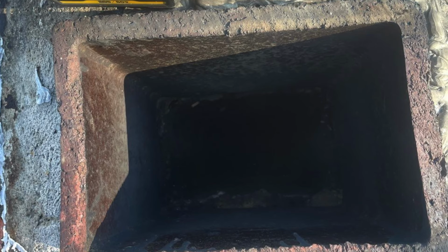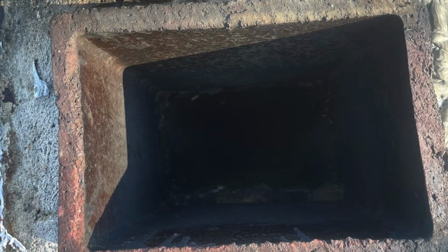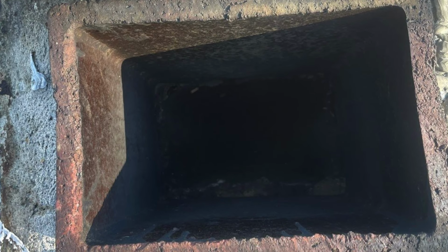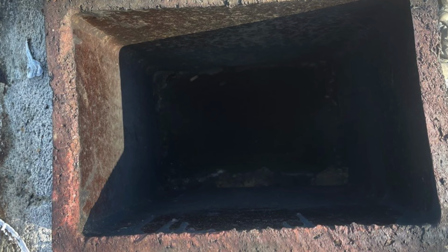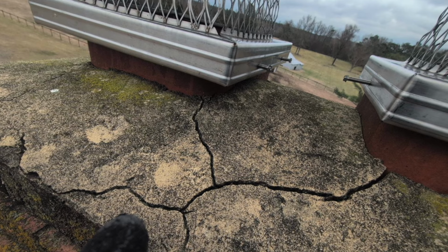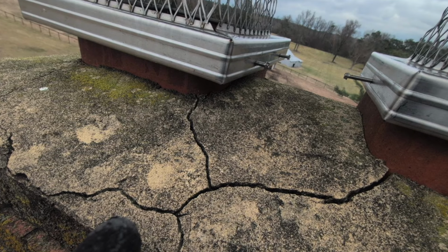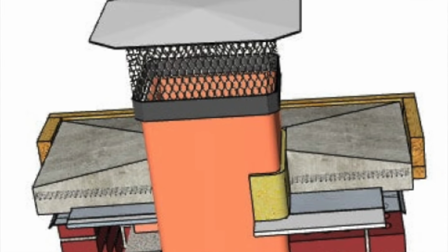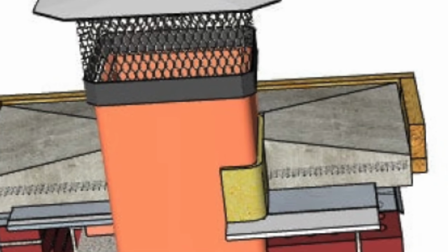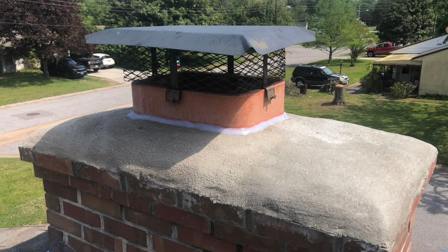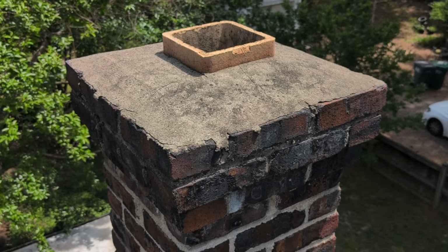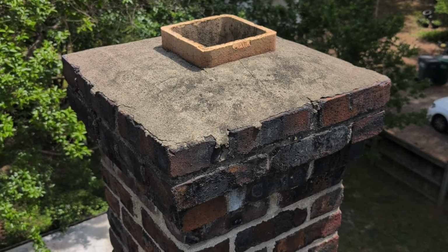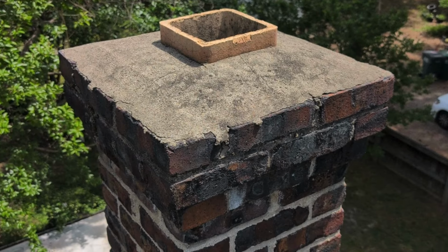Thermal expansion is a predictable and unavoidable behavior of vitrified clay tiles. If the flue cannot expand freely, the system will relieve that stress through cracking, lifting, crushing, deterioration, or long-term buckling. This is why ASTM C1283 and NFPA 211 require a bond break between the crown and the flue tile. Without this allowance for movement, failure of the crown or the liner is not merely possible, it is inevitable.